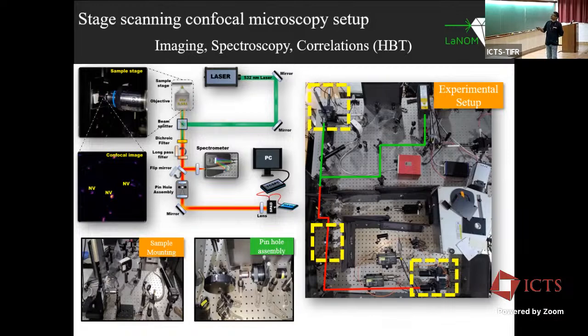So you have a laser, you excite with a high NA objective. The sample is here, the picture is given here. The sample is scanned on an XYZ stage. And you can collect this emission and send it to a spectrometer for spectral measurements, or send it to a single photon detector for lifetime measurements. And we can also do intensity correlation measurements.